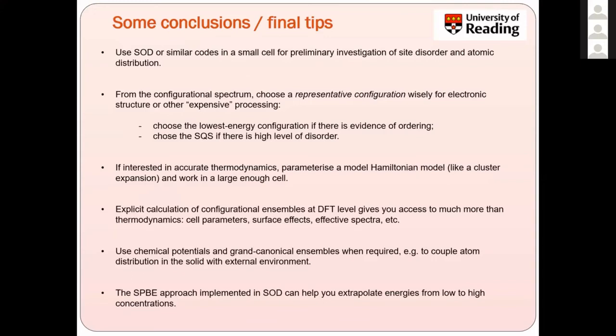If you have a lot of order in the system, of course, the lowest energy one is a good one. If you have a lot of disorder, then generate the SQS. You can do that with SOT as well, using GULP and SOT together. But bear in mind that calculating all the configurations in the ensemble using DFT is not just to calculate thermodynamics. You have access to much more. You can average anything, cell parameters, you can calculate surface effects, you can calculate effective spectra, and so on.